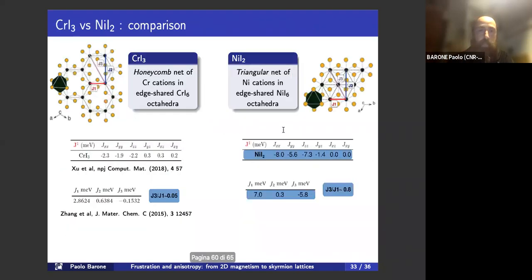So we can also compare with the chromium I3. As I said before, the main difference between the chromium I3 and the nickel I2 is the lattice. So we have a hexagonal lattice as opposed to the triangular lattice here, and also we have a different exchange path for the third nearest neighbor interaction, and as a consequence, the magnetic frustration is much smaller. However, the anisotropic exchange has also been calculated relatively recently, and in that case, chromium I3 also has an important anisotropic exchange contribution, which is of the same order of the single ion anisotropy. So it also contributes to the magnetic anisotropy of the system.